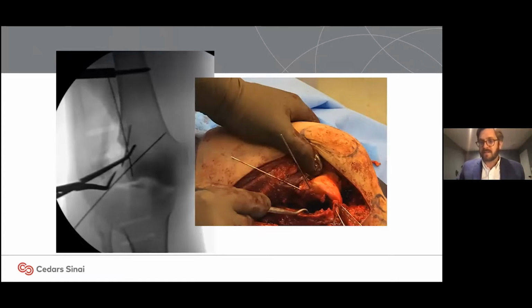This case differs a little bit from the previous two because this is, number one, an extremely large defect, and two, we have direct access to it. A couple things I do differently when I have direct access. One is that I'm much more likely to use a structural fibular strut or fibular allograft. Though I didn't in this particular case, it makes it fairly easy to wedge it in and gives pretty sound structural support. Second thing is that I generally go for something that's a little bit easier to handle.